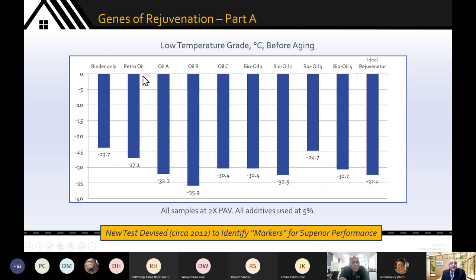What we did is we took virgin bitumen and artificially aged it, PAV aged it in the lab to simulate properties of 5 to 7-year-old RAP material gotten from roadways. We're using low temperature properties as a proxy here. Again, as I mentioned, you could use LAS, Fraass breaking point, ductility, any measure you choose, roughly the results are the same.